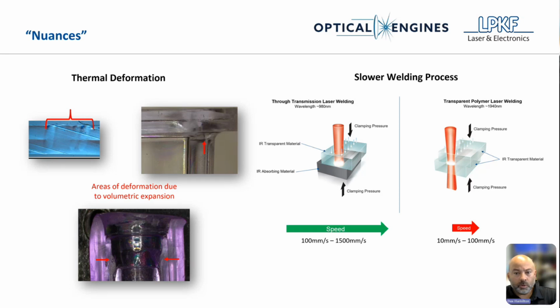With transparent polymer laser welding, it's a bit slower of a process. That's not detrimental, but it's good to be aware of the fact that it's about 10 times slower than through transmission laser welding. With that being said, we usually recommend to all of our customers that they look at through transmission laser welding first. And if that just absolutely can't fit their needs for their application, then we can look at transparent polymer laser welding.